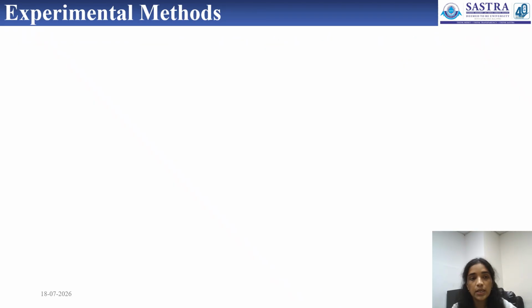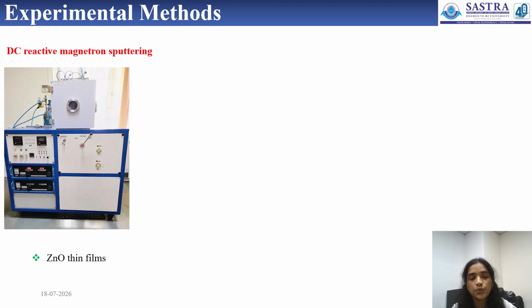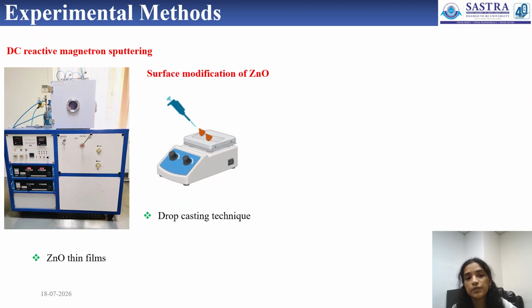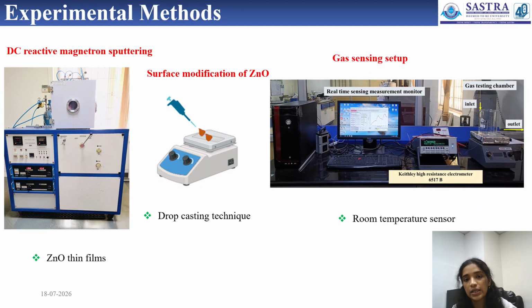For the experimental methods, zinc oxide has been deposited using DC reactive magnetron sputtering, and these sputtered zinc oxide thin films were further surface modified using the drop casting technique. These surface modified samples were utilized for the gas sensing measurement using a Keithley 6517B electrometer at room temperature.